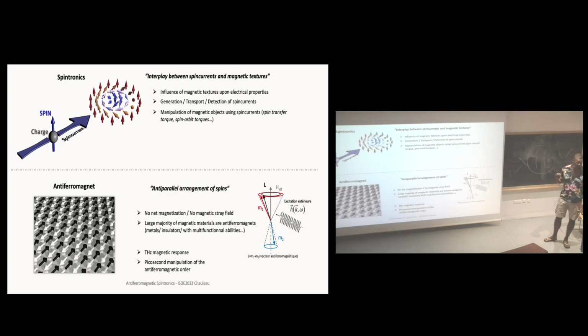And antiferromagnets are these peculiar magnetic textures where magnetic spins are antiparallel aligned. And this has striking consequences. The first one is there is no net magnetization. If you average out all those spins, then magnetization goes to zero, and therefore there is no stray field. So that makes them very robust, very silent. And what you have to know is that they stand as the large majority of magnetic materials. So in nature, antiferromagnets are quite numerous.